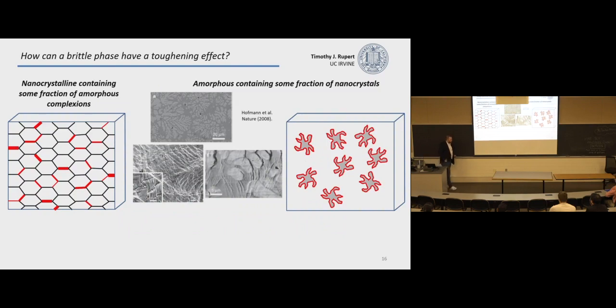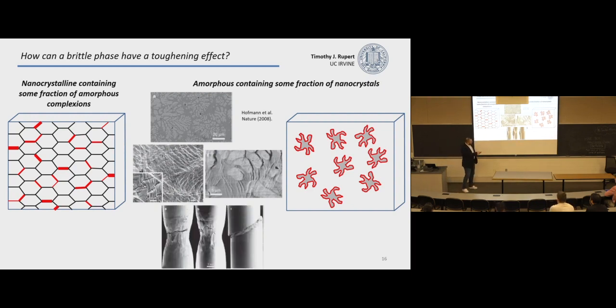We should think for a second about this, because one thing I'm telling you is that I'm adding an amorphous metal to my grain boundaries, which by itself is not a very ductile material, and that makes my material more ductile. It seems a little bit counterintuitive. But you can find other examples on the other side of this continuum. I'm saying that adding some fraction of amorphous complexions is good. People have shown that if you're looking at amorphous materials, adding some small fraction of nanocrystals can be good. In this case, this is a pure or regular amorphous material with a homogeneous microstructure, and it just shear bands. If you add in the nanocrystals, you can get much more plasticity there.